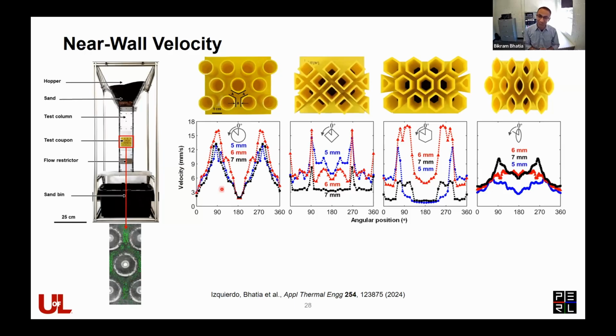Airfoil geometry is actually quite interesting. We were for some reason expecting the velocities might be much higher for airfoils. What we had in the back of our head was that the higher velocity, a streamlined flow, would result in a higher heat transfer. But the velocities were lower, and the variation in the velocity along the angular position was not that significant. So that we thought was pretty interesting.